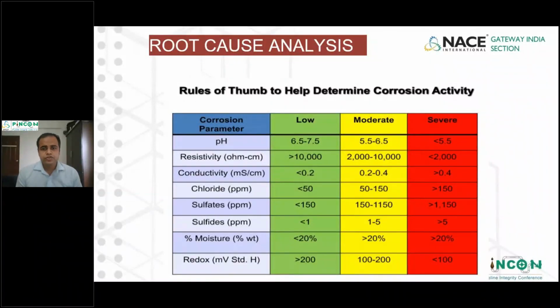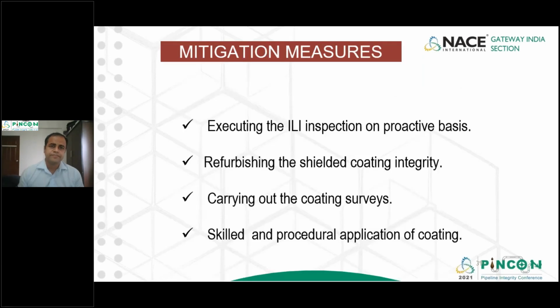I have established a rule of thumb by going through a lot of literature on the online available portals that if your pH is less than 5.5, the corrosion rate is very, very severe. Resistivity less than 2000, conductivity more than 0.4, and like that, moisture more than 20%. So these are all things I wanted to present to you as a part of the rule of thumb.